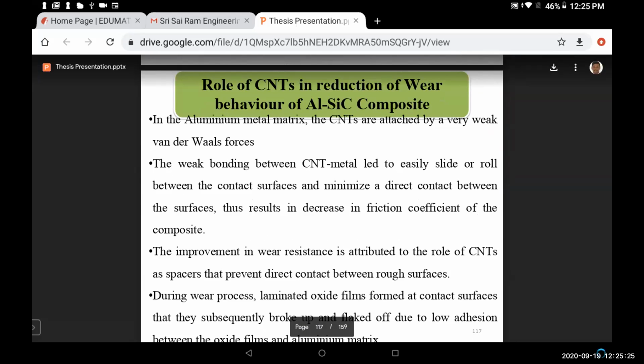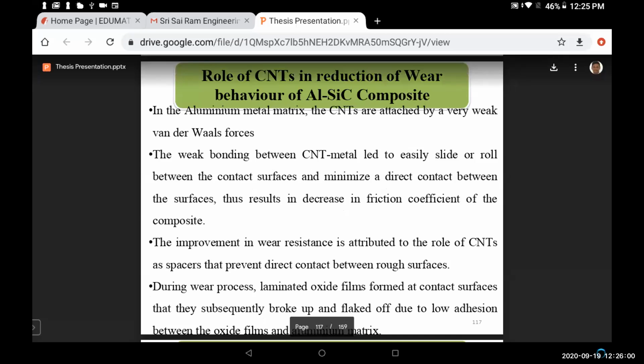So here is the role of CNT in reduction of wear behavior in aluminum silicon carbide composite. This is the final essence of the research. The weak bonding between the CNT and metal leads to easy slide or roll between the contact surfaces. So why does this aluminum CNT silicon carbide composite give a very low wear rate? This point is very important. The weak bonding between the CNT and metal leads to easy slide or roll between the contact surfaces and minimizes the direct contact between the surfaces, thus resulting in a decrease in the friction coefficient of the composite materials, which in the specific.